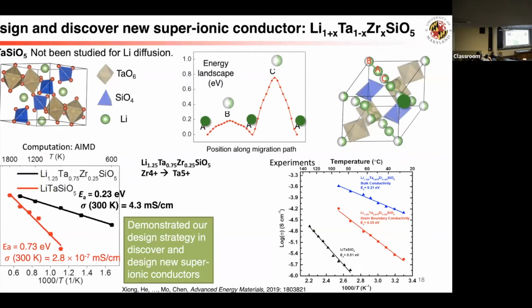But basically you also see that the original material is very low down here. And for the doped one, they cannot dope as high as we wanted, but basically you can see high conductivity and a low activation energy. Basically, it's a material that's really discovered by computation, then improved by computation, and then confirmed in experiments. So that's a successful example.